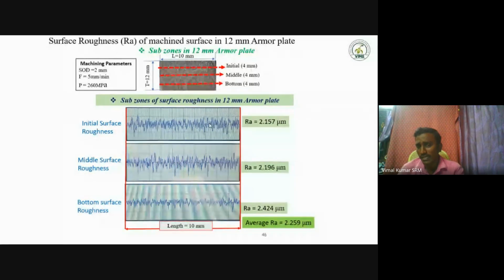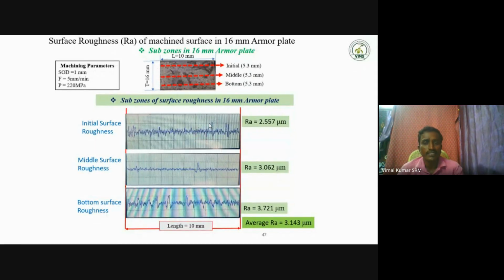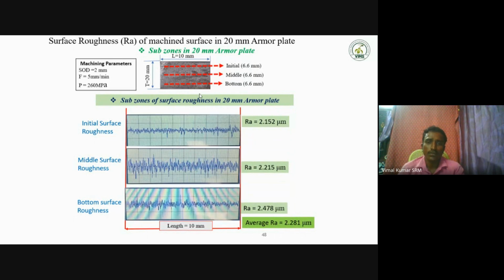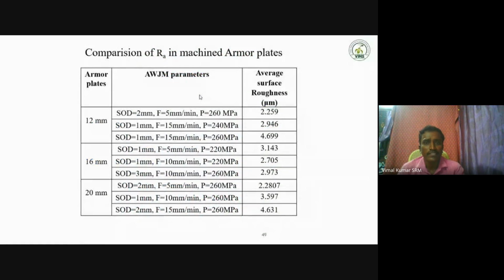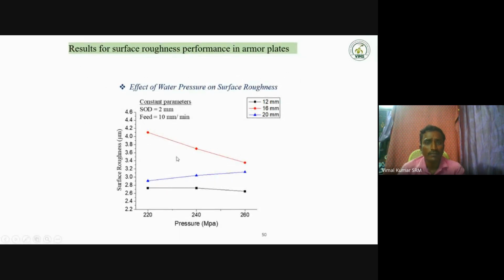This is currently done at our Kalasalingam Institute. This is the 16 mm plate surface roughness values, and the 20 mm plate surface roughness values. It's a comparison of surface machined armor plates. Here for 12 mm we can get the best, moderate, and worst, 3 different values. For the 16 mm plate also we can get 3 different surface values: best, medium, and worst. From the different values we can plot a surface roughness comparison with respect to pressure. As pressure values increase, do surface values increase or not?